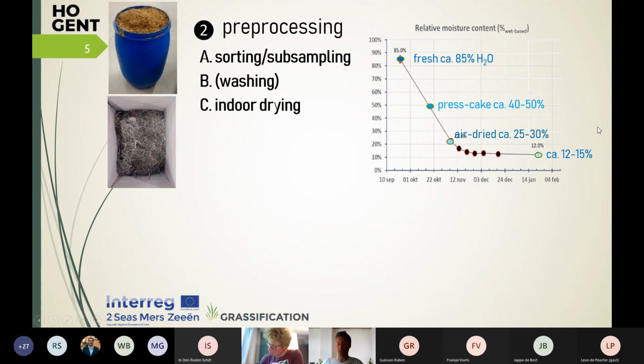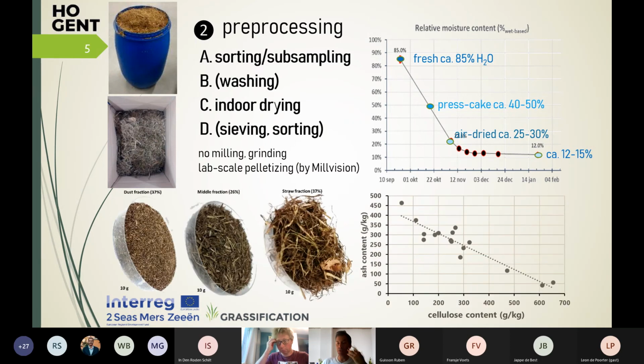So we started with fresh grass of about 85% moisture. Also the press cake, which is somewhere in between, so about 50%, where 40% of the liquid had been extracted. And then the air-dried grass had about 25 to 30% of moisture. But for the experiments, we needed grass that was fairly dry, so in the range of 12 to 15%, except for the mineral experiments, which I'll also show later.